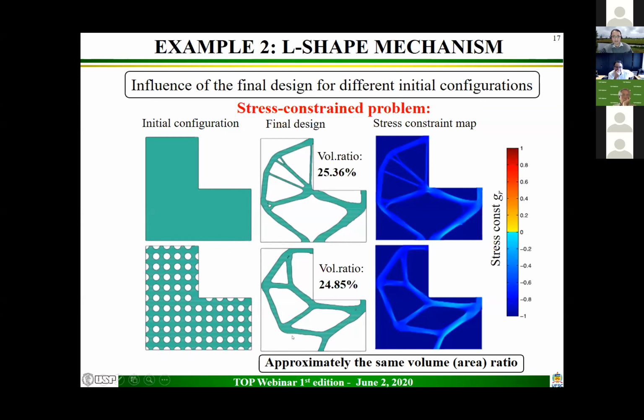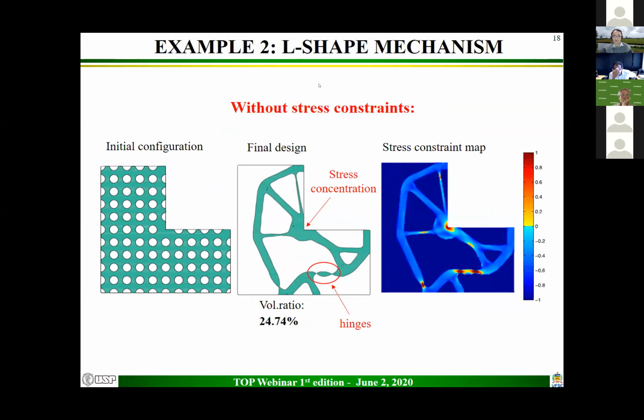And then we solve it again with this initial configuration with holes. We come up with this topology here, which is different. However, both of them have approximately the same volume ratio. Both of them are hinge-free designs and they satisfy the stress constraint. And this example shows the influence of the initial configuration on the final design. We have solved the same problem without the stress constraint. So we come up with hinges and the stress concentration here.